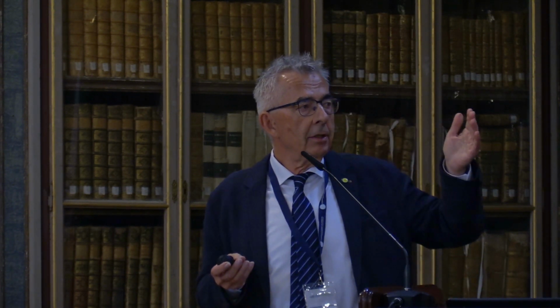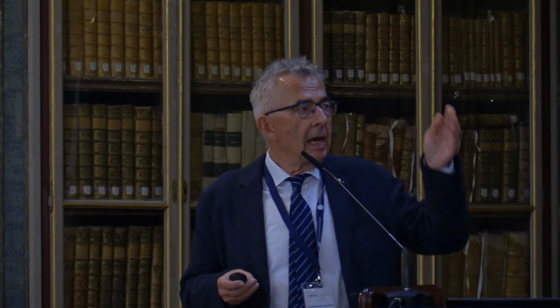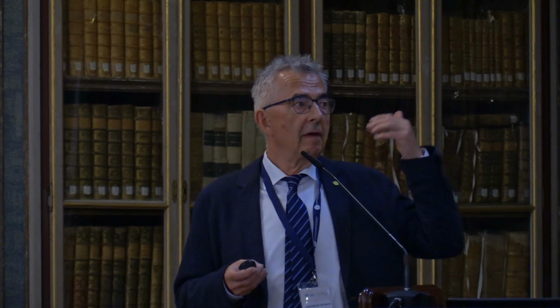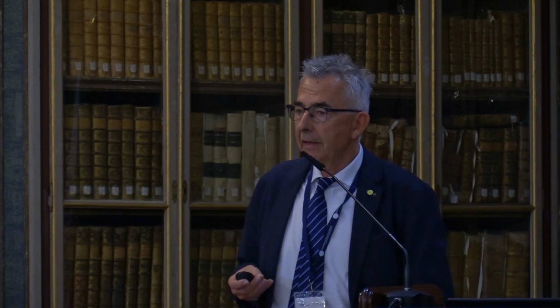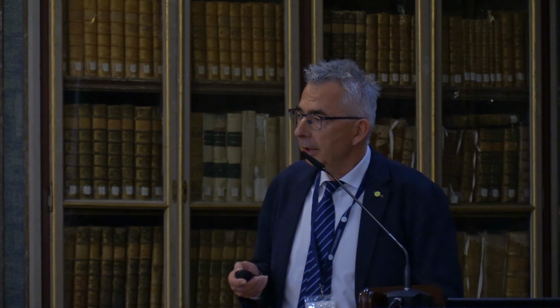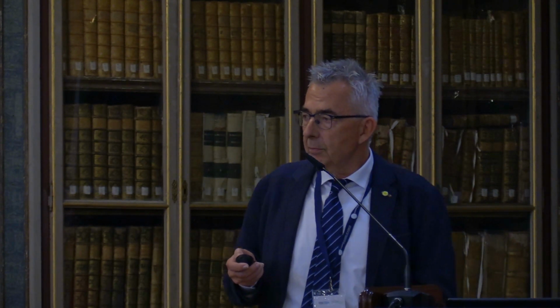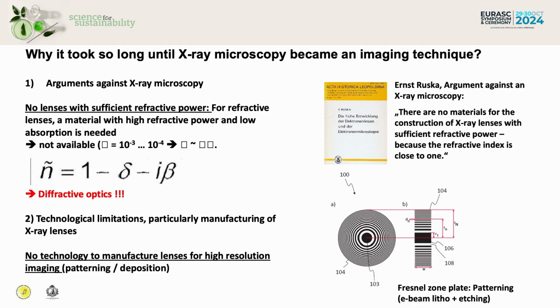particular focusing optics. It's a condenser which brings as much as possible photons to the sample, and it's a lens, because refractive processes do not work. We have a Fresnel zone plate, and the Fresnel zone plate is a diffractive optics with hundreds of concentric rings, and at each ring, at each zone, there's a diffraction process to focus. Now, very often, colleagues are asking me why it took so long until X-ray microscopy became an imaging technique.